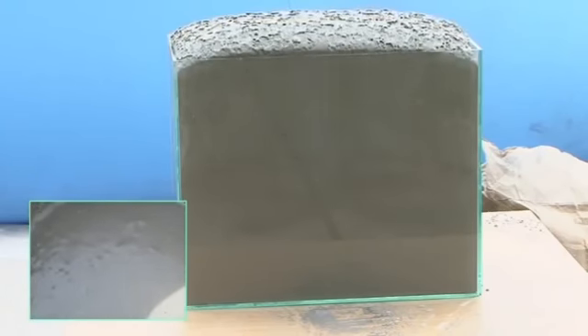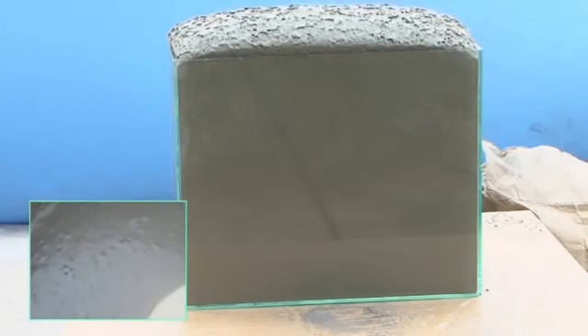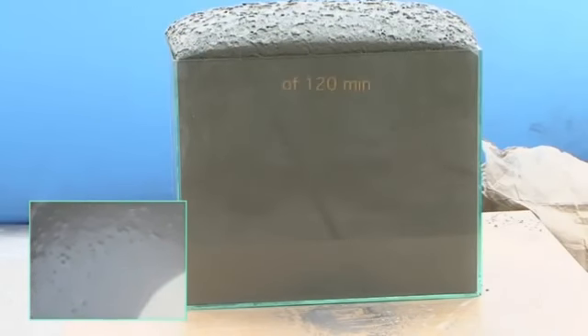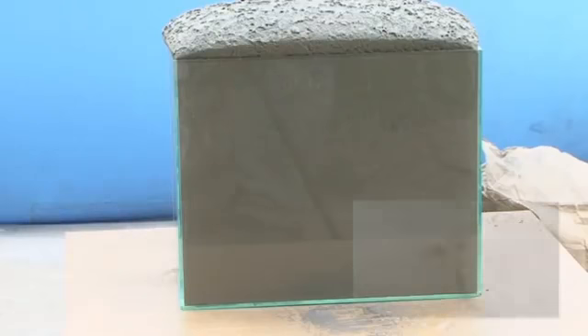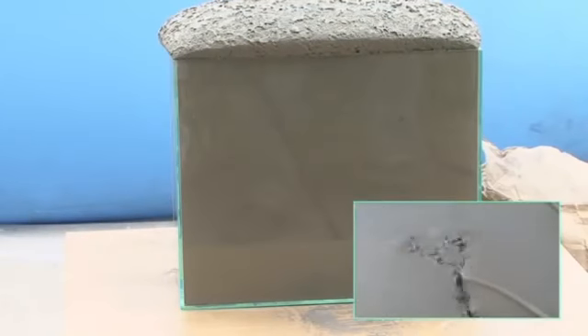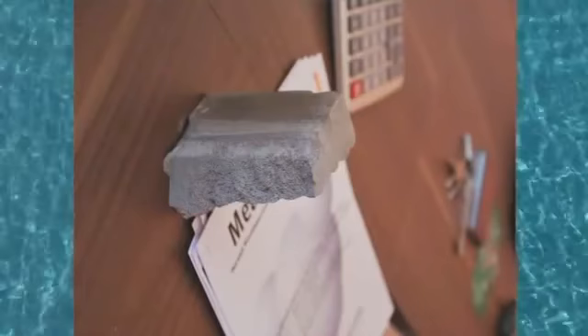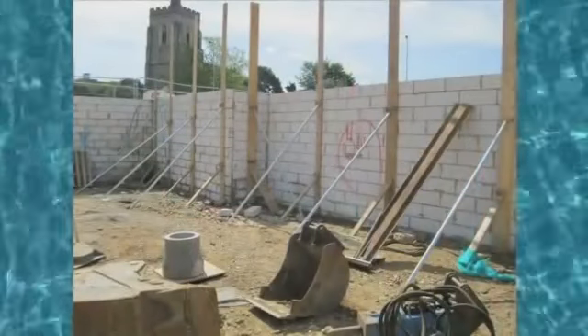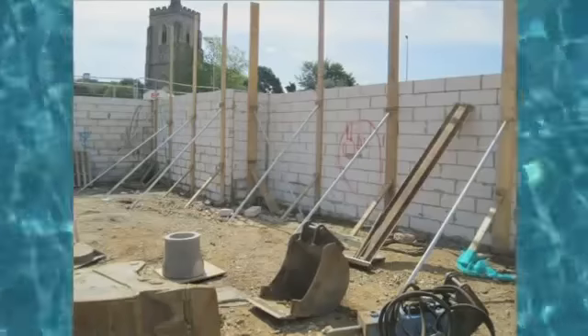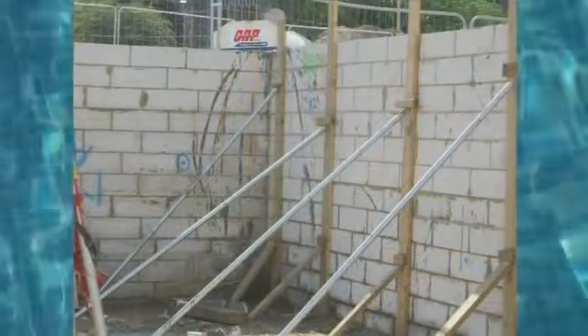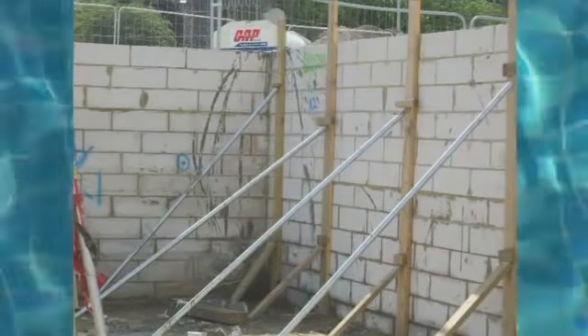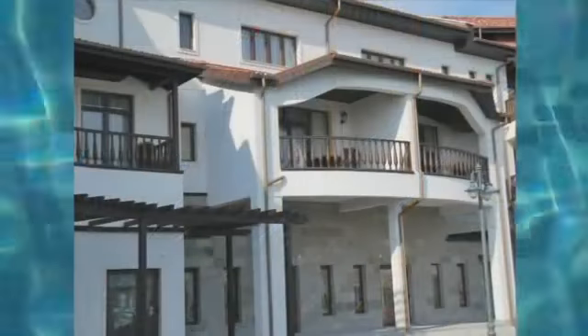The intense mixing of the CFC dry mixture with water leads to the preparation of the gas cellular concrete, which matures after it is poured, increasing its volume 2 to 4-fold and gets its initial hardness. The mix of CFC with water is ready for forming of different construction products: blocks for walls, overhead covering and partitioning slabs, arches, and so on.